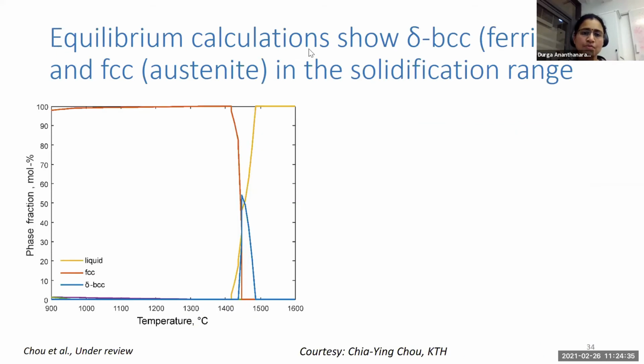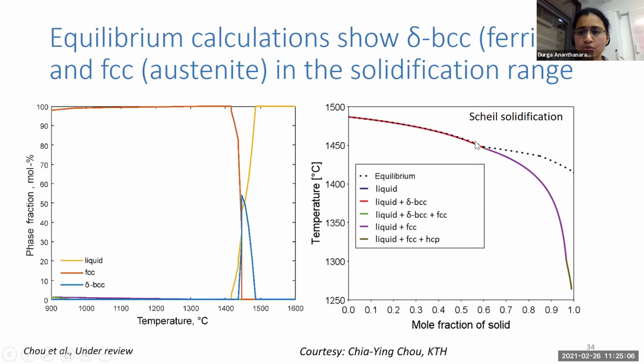When we look at the equilibrium phase fraction of this particular tool steel, we see that at high temperature in the solidification range, first we have the delta BCC, the ferrite, and then the red one, the FCC or austenite, also starts to form in the solidification range. And then after some point, the ferrite dissolves. So if we typically start with this information and want to do Scheil solidification to predict the phases and segregation, we see that even there, first delta BCC or ferrite would form, and then FCC forming and then other phases maybe. So if we just used Scheil, then we will predict that delta BCC, FCC, HCP form at the end of solidification, which is of course not what we see from the experiments. We should see predominantly austenite, which would then transform to martensite.